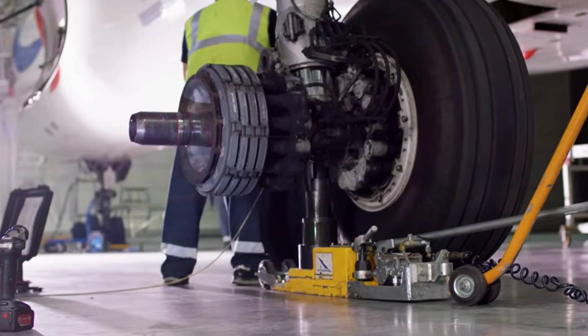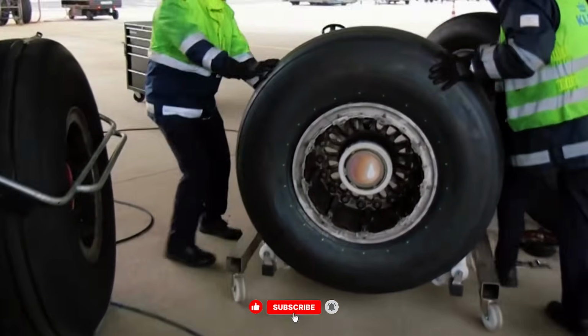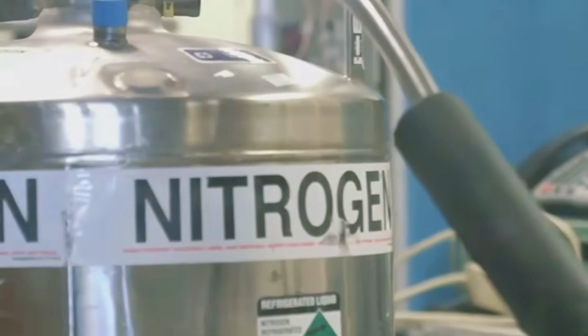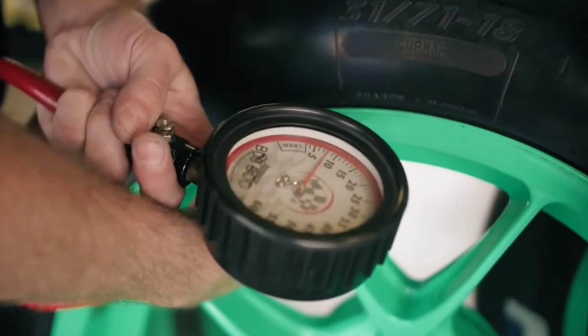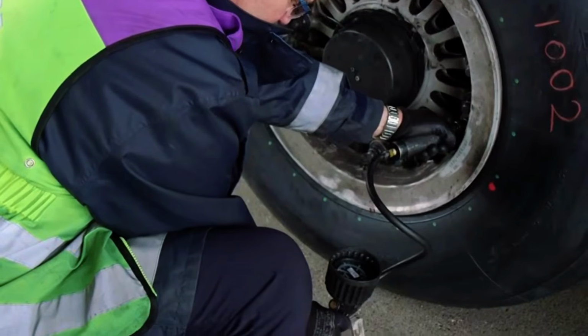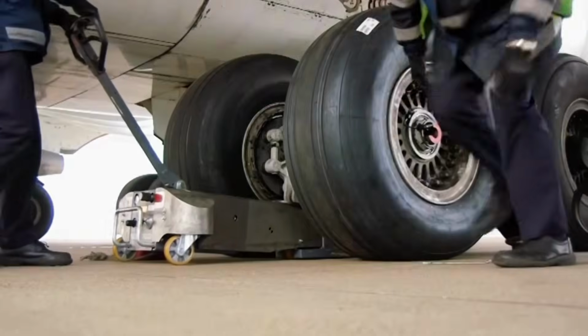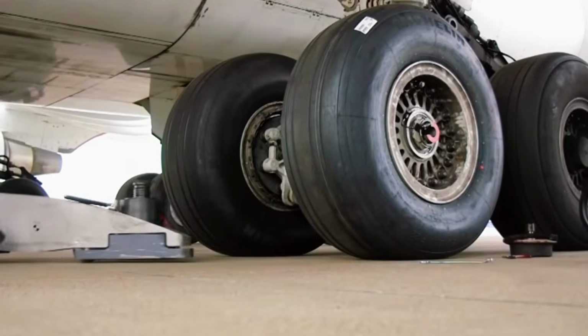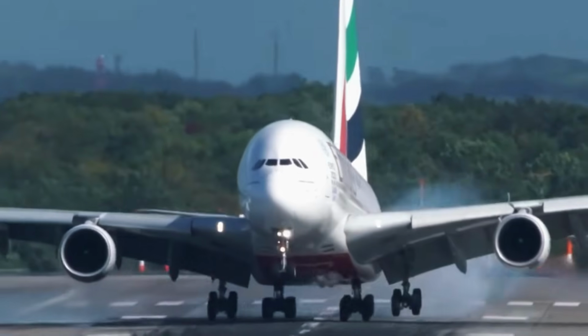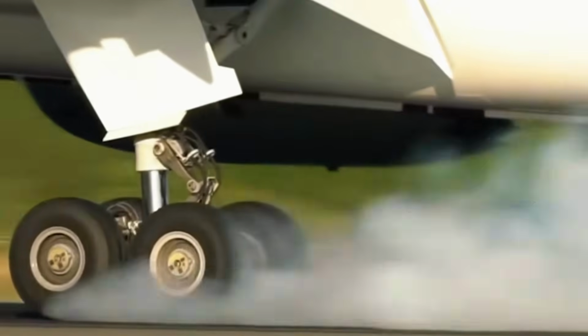in a controlled sequence. Then inflation begins, not with compressed air, but with dry, pure nitrogen. Nitrogen expands less than air when heated, making pressure more stable across the extreme temperatures of flight and landing. It contains no moisture, eliminating internal corrosion risk. And by removing oxygen entirely, it eliminates any risk of ignition, critical given the extreme heat generated by aircraft brakes during landing. The wheel assembly is dynamically balanced to eliminate vibration at landing speed.